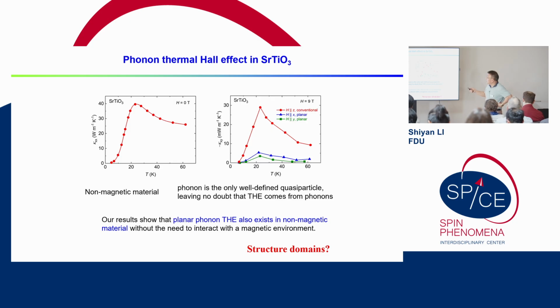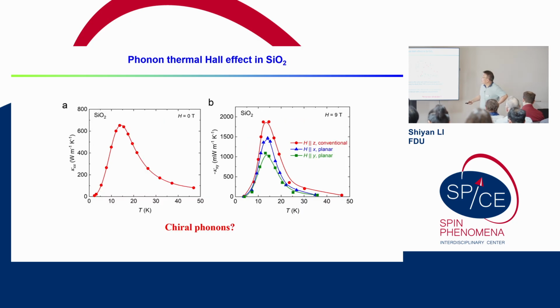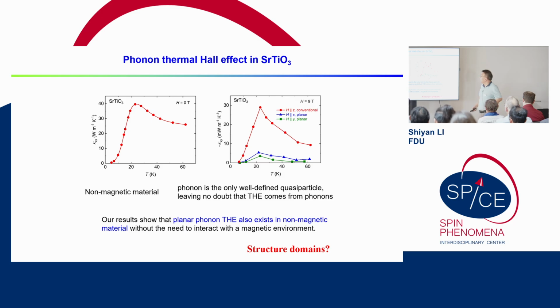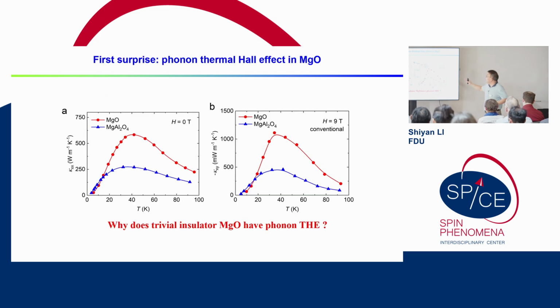Then we started writing the paper. I asked the students, we should have a reference compound in which there are no chiral phonons, right? And there's no thermal Hall effect. So we checked a list of insulators. MgO is very trivial, right? You look at it from everywhere, it's very trivial. So we measured it, there's some thermal conductivity, and it has a very large thermal Hall. That was very surprising, our first surprise. Why does this trivial insulator, MgO, have a phonon thermal Hall effect? We measured MgAl2O4 later to check it, to try to measure more single crystals.